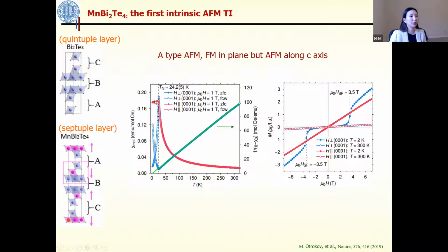intrinsic antiferromagnetic topological insulator. It was made by this so-called 1-2-4 septuple layer building block, right? It orders below 24 Kelvin with a so-called A-type antiferromagnetic structure, that is, spins ferromagnetically aligned in the AB plane, but antiferromagnetically coupled along the Z-axis. It has a spin flop transition. You can see it has a spin flop transition around 3.5 Tesla and a saturation field around 8 Tesla when the field is applied along the Z-axis.